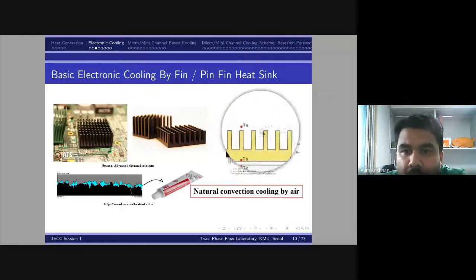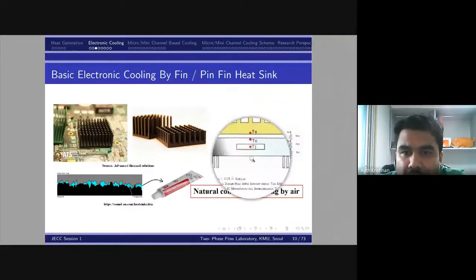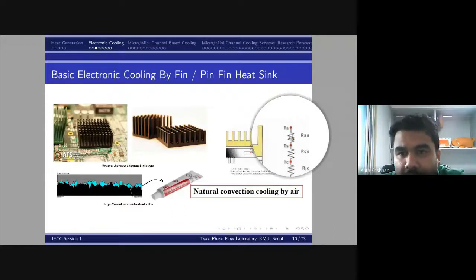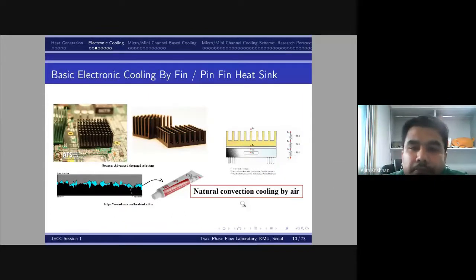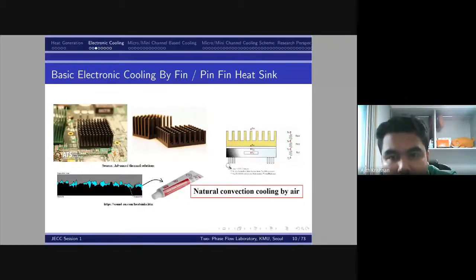And this is one of the models of that simple electronic cooling by pin-fin heatsink. You can see here showing the resistance model. The three resistances: one is the interface resistance, the other one is the resistance of the heatsink, and this is the resistance of the chip top surface. So it's simply natural cooling by the air, simply natural convection, and the heat transfer coefficient will be very low, nearly in the order of hundreds, and also the maximum heat that it can dissipate will be around 10 to 20 watt per centimeter square. But our requirement is around 200 or 300 watt per centimeter square. So this is not an efficient method, and it needs to be revised according to the new device level and device performance in order to dissipate more heat.